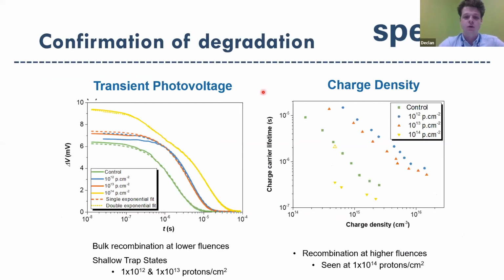So we did some work with Matt Carnie's group at SPECIFIC. We did transient photovoltage and charge density measurements and found that as you increase the fluence up to 10^14, the charge lifetime decreases, and we get a double exponential fit on the TPV, which indicates interfacial recombination and an increase of it. With the Raman data, we came to the conclusion that increased proton bombardment destroys the spiro layer. This leads to an increase in recombination, which leads to a decrease in device performance.